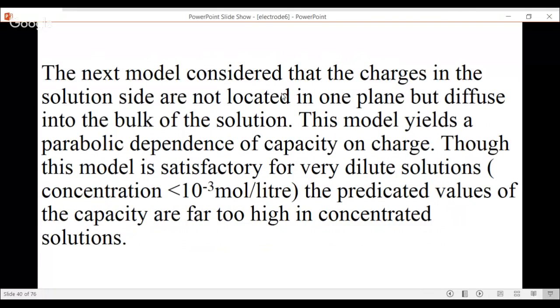The next model considered that the charges in the solution side are not located in one plane, but diffuse into the bulk of the solution. This model yields a parabolic dependence of capacity on charge. Though this model is satisfactory for very dilute solutions, of the order of 10 to the minus 3 moles per liter, the predicted values of the capacity are far too high in concentrated solutions. So in concentrated solutions, the predicted value of the capacitance is high compared to the experimental value. So this model also is deficient.